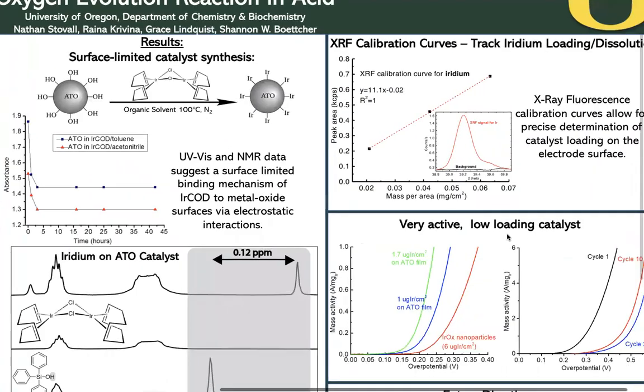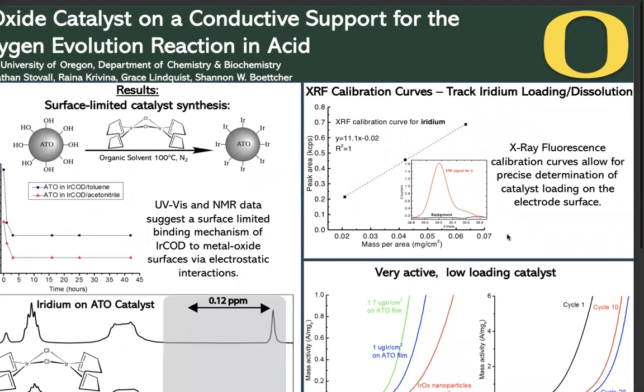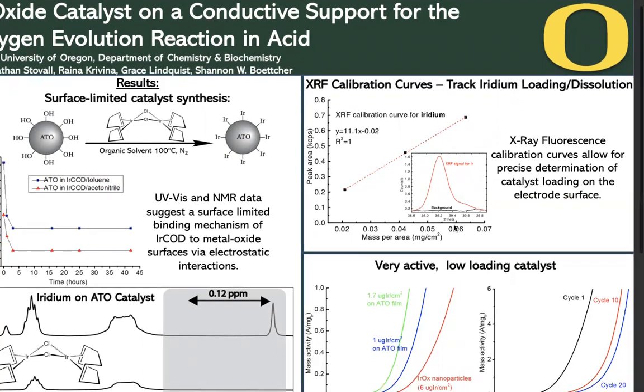We also developed an iridium calibration curve to determine the loading of our catalyst on our electrodes. This is done using X-ray fluorescence spectroscopy, where we can relate the peak area of the XRF data to the mass of the catalyst. This allows for quick determination of mass loading and a means to compare our catalyst to other iridium catalysts as a function of mass.